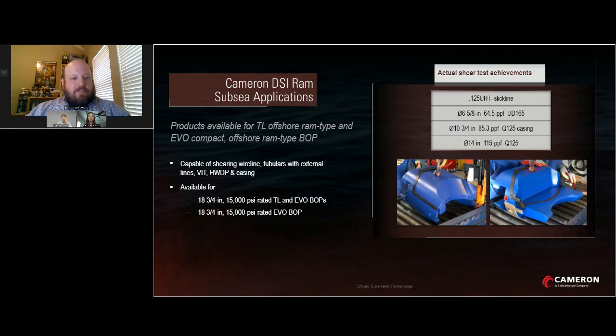Because we needed the larger range of shearing, we also had to address the temperatures that come, and we had to reduce the size of the packers on the side to clear that larger tubular in the existing wellbore we have. We accomplished this by editing the compounds we use, the way we mold it, and the way we build it into the ram. But we were able to achieve API 16A, or the American Petroleum Institute Specification 16A, 4th edition PR2 at 30 degrees Fahrenheit low, 200 degrees Fahrenheit continuous, and 350 degrees Fahrenheit extreme temperature rating. So we were pretty excited about that.